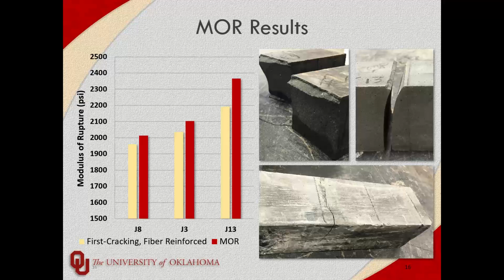So when we started putting type 3 in there, we were able to get closer, but it didn't have as much of a benefit as we had hoped in getting that early age strength. But the late age strength was still very similar to J3, where it was all type 1.